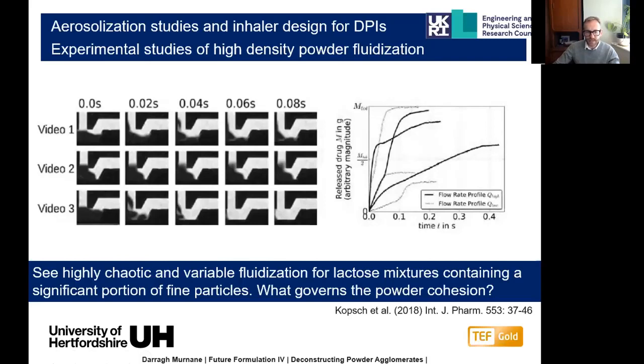we can see that there's quite chaotic behavior in the aerosolization events. So throughout the video, you see plugs of powder that become emitted. In some instances, and in other powder fills, the powder doesn't even empty at all in the same time frame. So it's a very variable process. It's a highly chaotic, highly variable fluidization process for those lactose mixtures that contain those fine micronized particles.